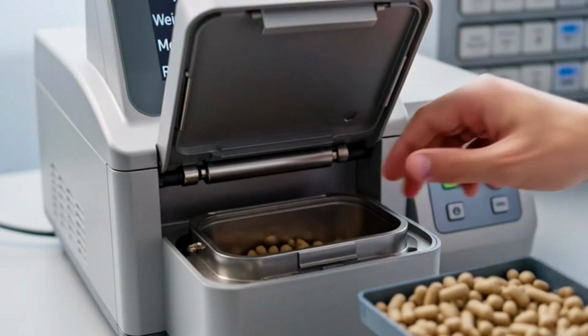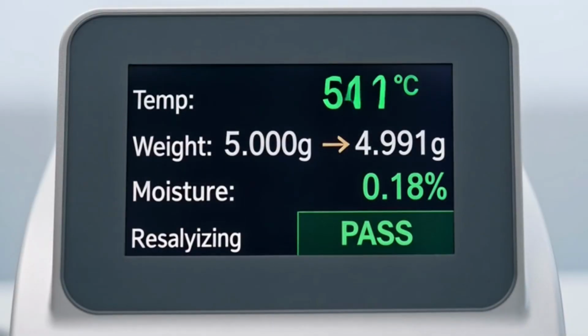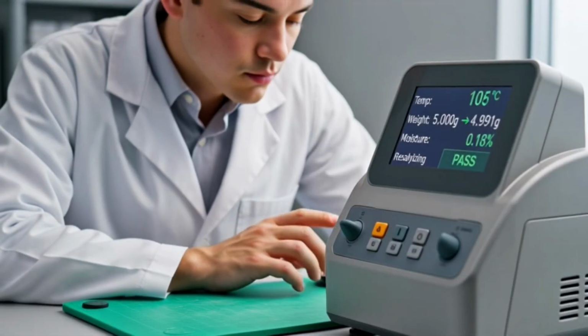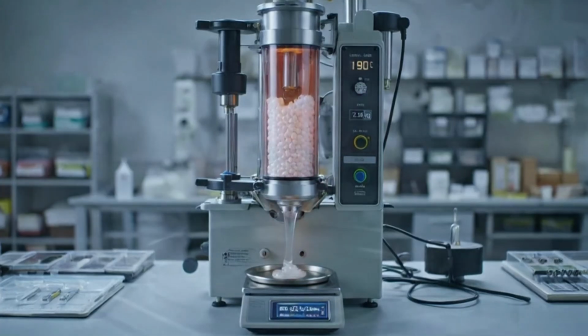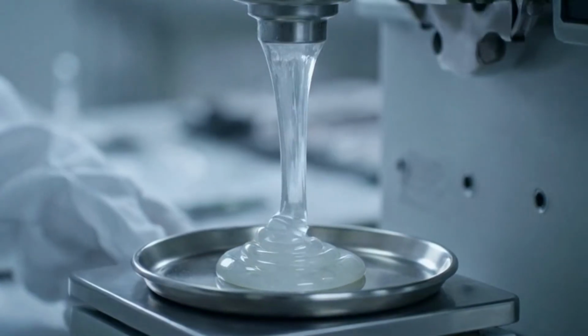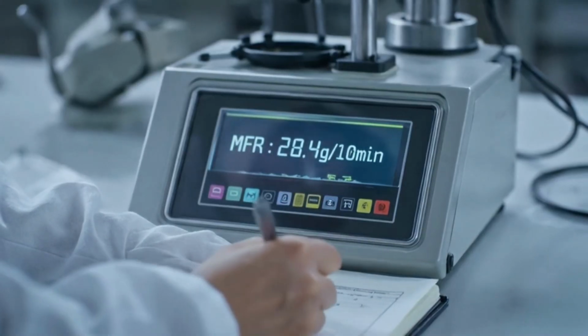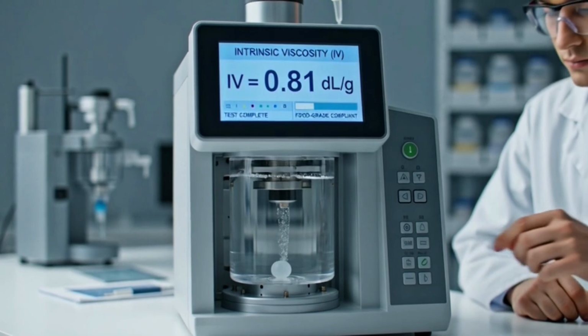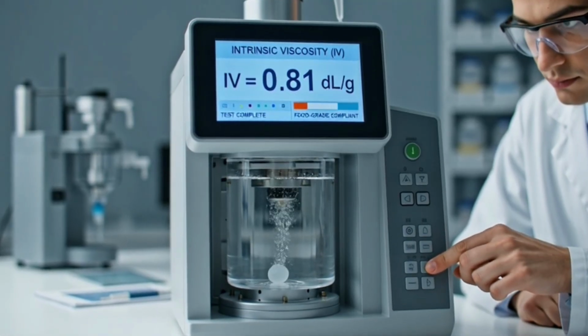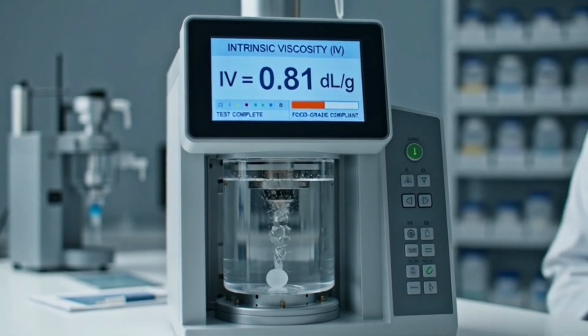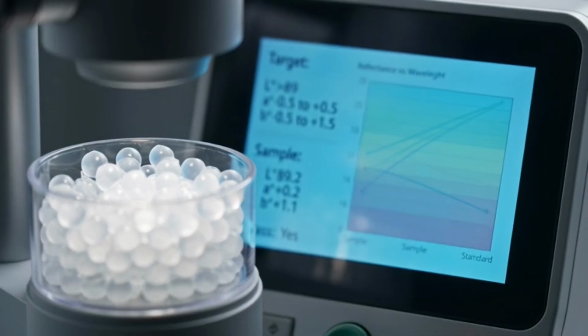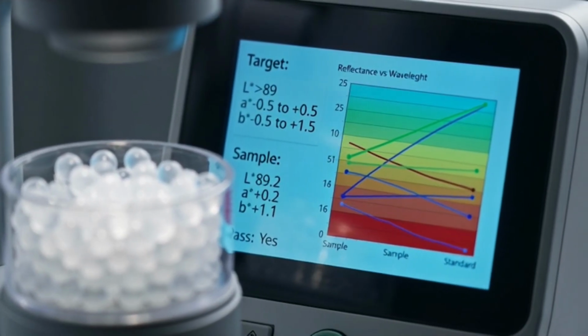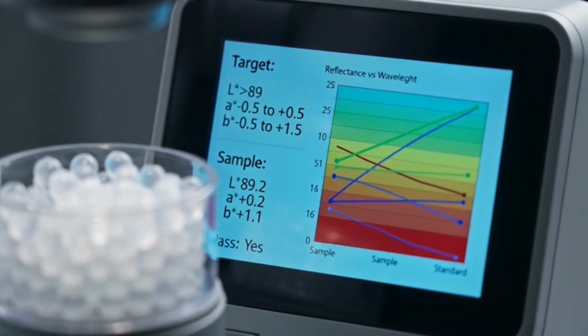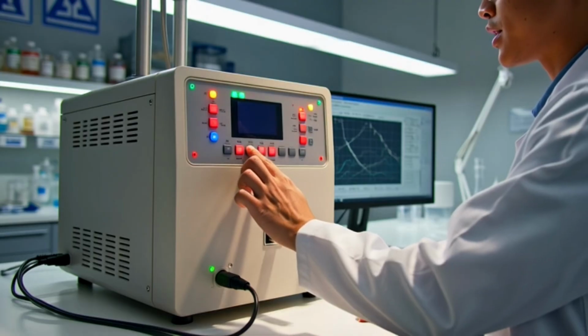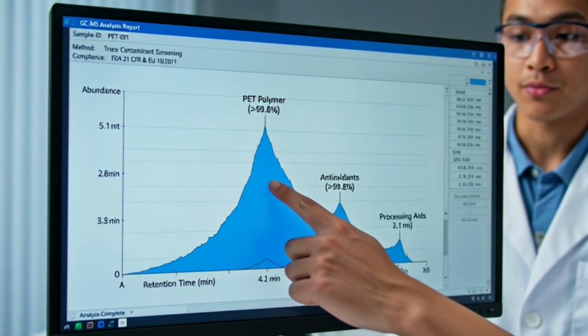Moisture content is critical. Our specifications require 0.3 or less. Melt flow rate testing ensures material will perform correctly on customer equipment, critical for industrial buyers. Intrinsic viscosity analysis confirms molecular integrity, essential for food-grade material certification. Color analysis ensures optical consistency, critical for transparent food contact applications. Gas chromatography mass spectrometry analysis detects trace contamination at parts per million sensitivity.